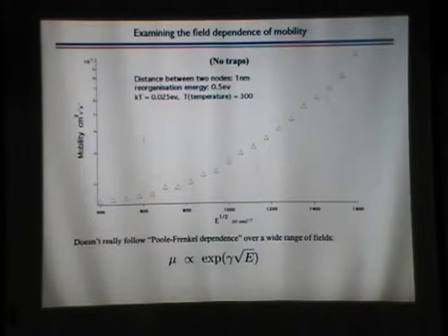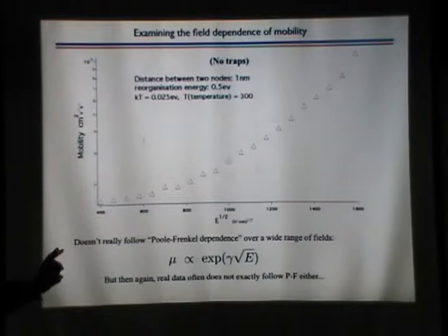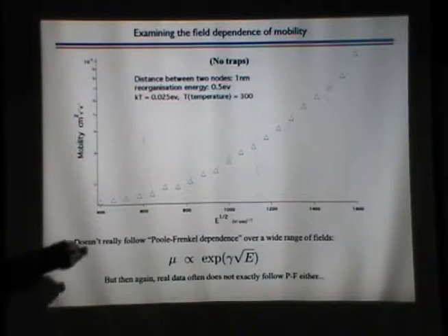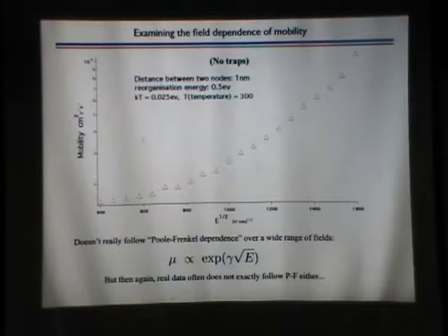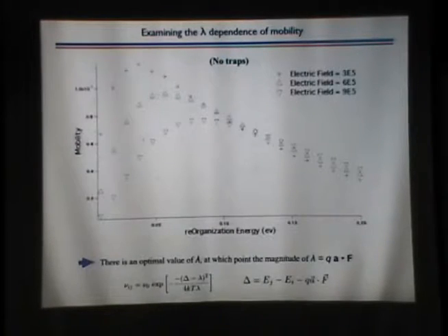And again, I told you that under the Gaussian disorder model, where there's no correlation, you don't get a perfect fit, and we see this here as well. We have not put any correlations in the energy, so it's not a perfect straight line, but it's pretty close. And in reality, when you measure a real material, you also don't get a straight line, because oftentimes those correlations aren't quite perfect, or they're not homogeneous. So we think that this is at least a test that our model is fairly reasonable. And there were no traps in this model, we just had the main band.